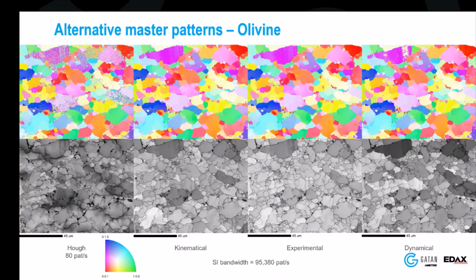So here you can see this is the experimental pattern. Here's the dynamical simulation, and here you can see the dynamical simulation is actually having problems in some areas. But because the experimental actually matches it better, it's not having the issues here. So in this olivine sample, we're getting really good indexing over the whole area. Where the Hough was having some problems, like here, the Hough was just not doing its thing. And here you can see that we're getting nice consistent data over the entire area when we use spherical indexing. So by combining spherical indexing with the experimental master patterns, we're getting better information off of